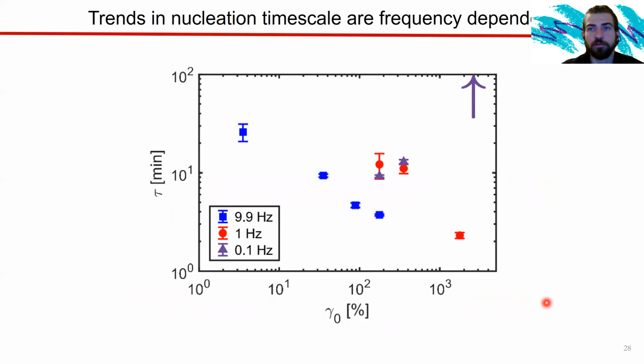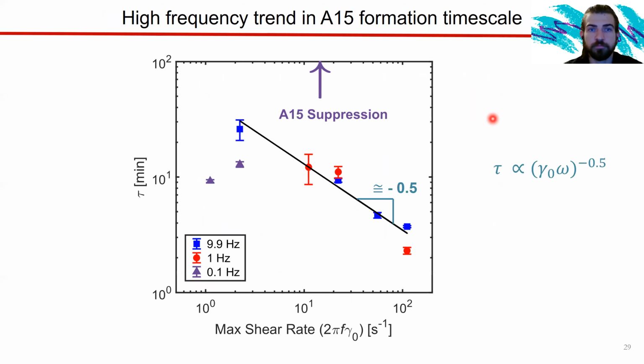So what I'm going to do is take all these time scales from the Avrami fits from all the different shear experiments we did, and plot them on this graph where we have just strain percent on the bottom axis. And we have our 10 Hertz samples in blue, 1 Hertz in red, and 0.1 Hertz in purple. And this arrow I'm going to plot here shows the scenario where we didn't observe any A15 formation over the duration of the experiment. So I'm going to argue that the time scale here is much longer than 100 minutes.